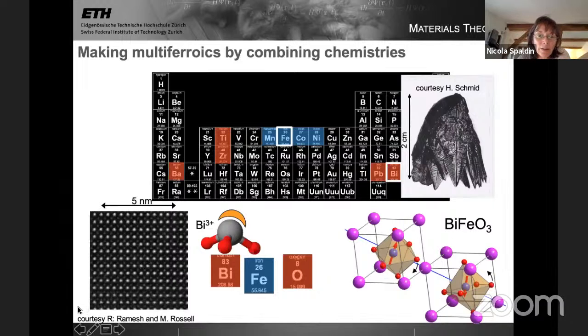And here's a high resolution transmission electron micrograph grown in the group of Ramesh, the microscopy from Marta Rossel. The white dots here are the bismuth atoms. The very faint white dots are the iron. And you can see that this is a thin film and it's really, really perfect. So this advance in materials synthesis, in particular in thin film growth, was really what allowed the properties of multiferroics to really be demonstrated.